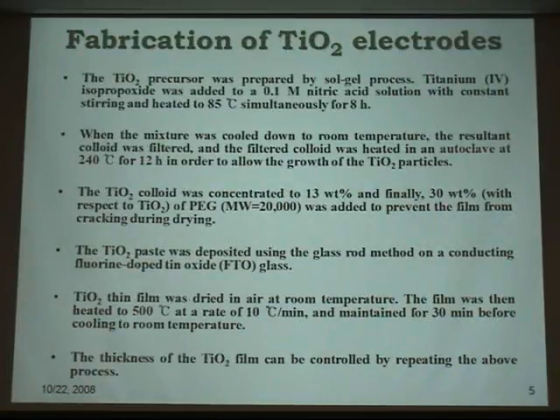Now this is a very systematic way you can find in the existing literature to make a titanium dioxide, anodized titanium oxide film. The pretty standard method is to make a precursor first and you autoclave at a certain temperature. And this temperature is very critical because later you will find the morphology and surface area, etc. depend on your autoclaving temperature.